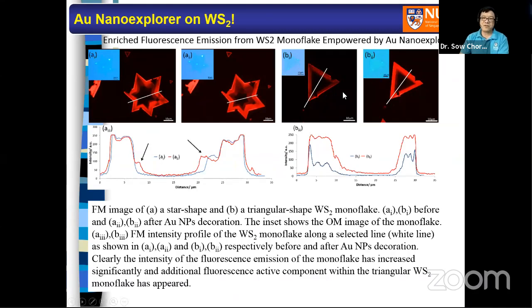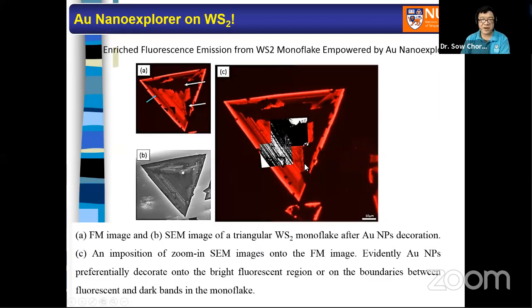B1 is the fluorescence image of a triangular shaped WS2. Then she decorated the whole thing with gold nanoparticles, and you see that the nanoparticles help to enhance the fluorescence emission of this particular piece of WS2. More importantly, if you look at A1 and A2, can you see that in A1, the interior region of the Star of David doesn't show very distinct fluorescence. After the gold decoration, it reveals what happened, and we find something very amazing.